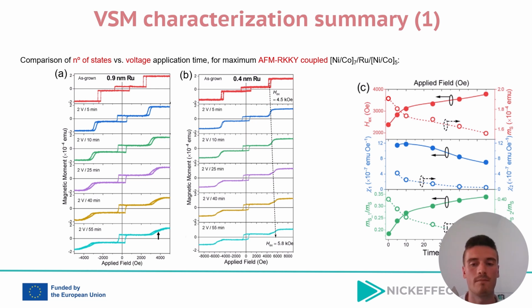Panel C quantifies key magnetic parameters over time, such as the exchange field in red, the susceptibilities Chi1 and Chi2 in blue, and the normalized remanent magnetizations, MR1 divided by MS and MR2 divided by MS, marked in green. These results indicate that time-dependent modulation of magnetic properties could be achieved in these multilayers, which comes along with the multi-state switching of these antiferromagnetically RKKY coupled cobalt-nickel multilayers.